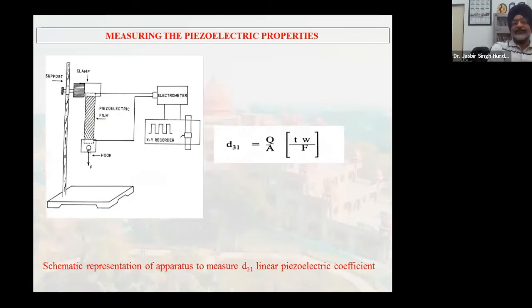Okay. Now this is the setup that was used to measure the piezoelectric coefficient. Here we have the polymer film that has been stretched and held with 2 plastic clamps, and here we have a hook. When we place a weight here, the film gets stretched. When this film gets stretched, what will happen? There will be a piezoelectric current flowing in the circuit, which goes through an electrometer and is recorded on an XY recorder. From there we are able to measure the piezoelectric coefficient.